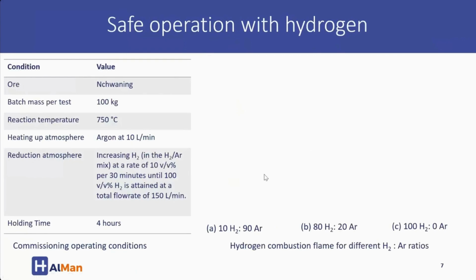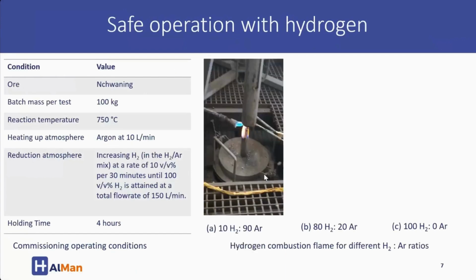But before that, we had to make sure it was safe to operate with hydrogen. One way of doing this was slowly increasing the ratio of hydrogen to argon, and using a pilot flame to ensure any unreacted hydrogen got combusted fully.